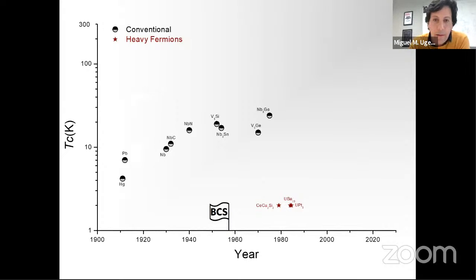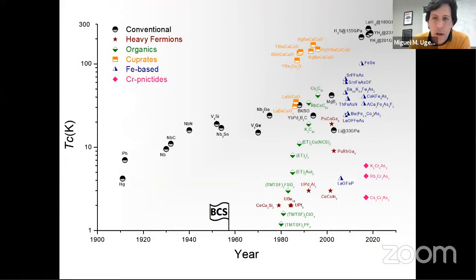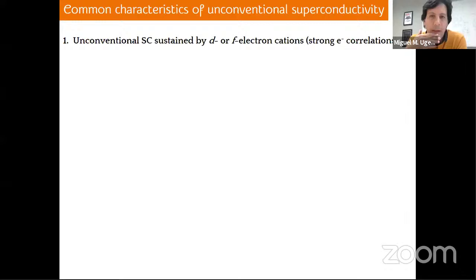So it's interesting to see that it took 70 years to discover these materials, because after that, now we know that there are many different families of unconventional superconductors. For example, you can see the remarkable example of cuprates with very high critical temperatures, or the family of iron-based superconductors, which were discovered in 2008. So as you can imagine, the superconducting properties of all these families are quite diverse. However, there are certain common characteristics of most of these unconventional superconductors. One of them is that unconventional superconductivity in these materials is generally sustained by d or f electron cations. There's one remarkable exception, which is twisted bilayer graphene, as you all know. But in general, the d and f electrons basically drive the superconductivity in these materials.